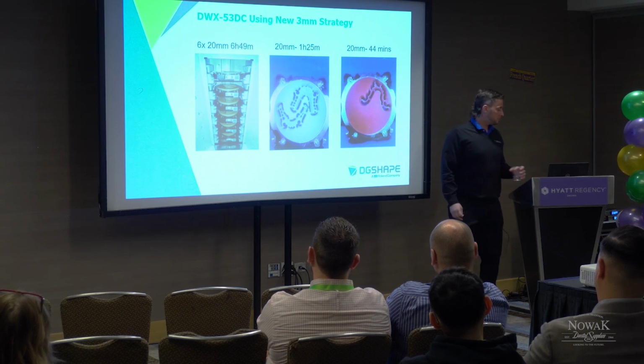Some other things that I'll mention, I talked about the denture base in around 1 hour. We are able to mill a full arch of denture teeth. If you're placing those teeth in an appropriately sized puck, that means if the tallest tooth is 12 millimeters, we're not putting it in a 20. If we're using a 12 or 14 millimeter puck, we're able to mill that full arch of denture teeth in 30 minutes. So 1 hour denture base, 30 minute set of teeth. Hour and 30 minutes, we have a fully digital denture that you can cut out and begin assembling.